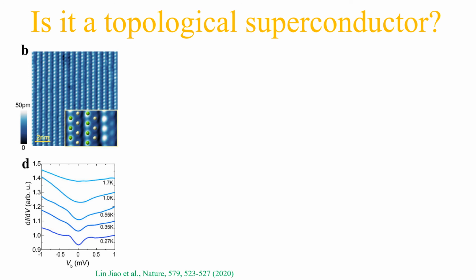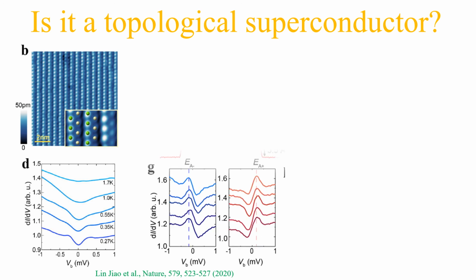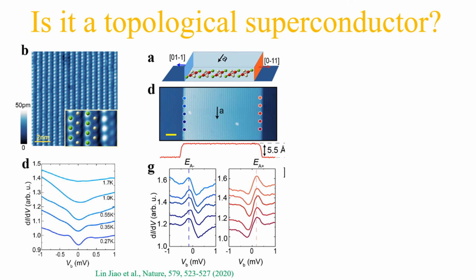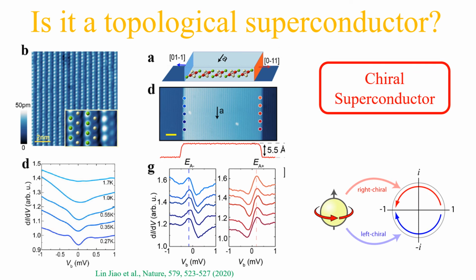Long story short, when they put the STM tip in the middle of the sample, it shows a very nice signature of superconducting energy gap. But when they put the tip on the edge of the sample, they observed antisymmetric in-gap structure. This indicates it's a chiral surface state that is consistent with a chiral superconductor, which is a type of topological superconductor that can host Majorana fermions, and therefore it has the potential to be used to build quantum computers. So that was a really big surprise. This discovery caught a lot of attention in the community. Many groups started working on this, and a lot of papers were already published. I think the momentum has just been built, and a lot more are coming on the way.